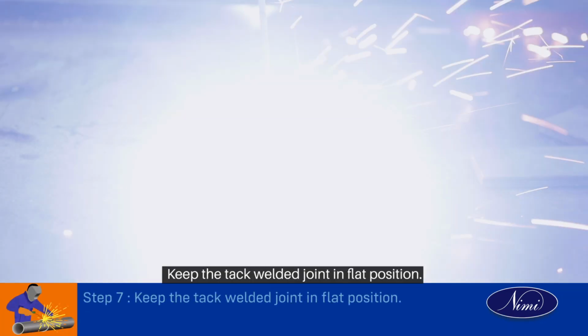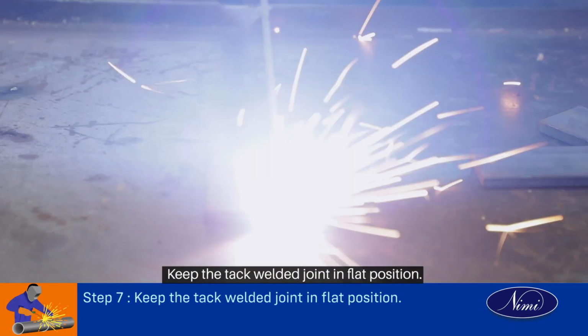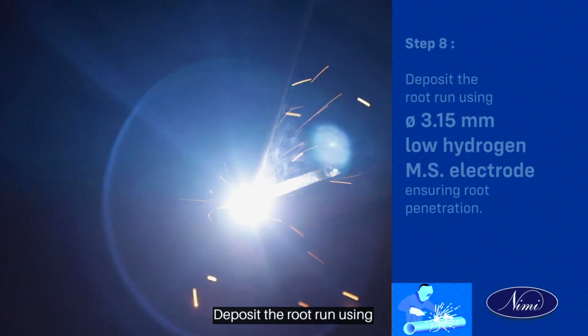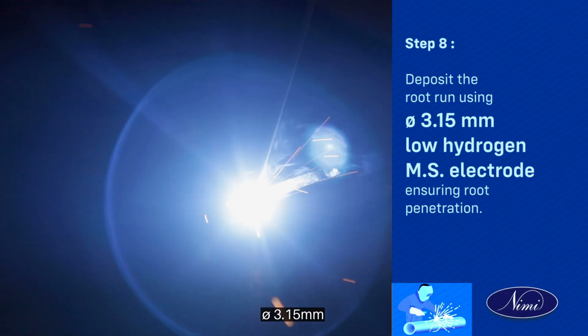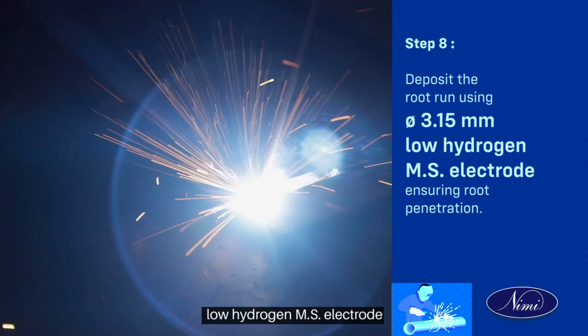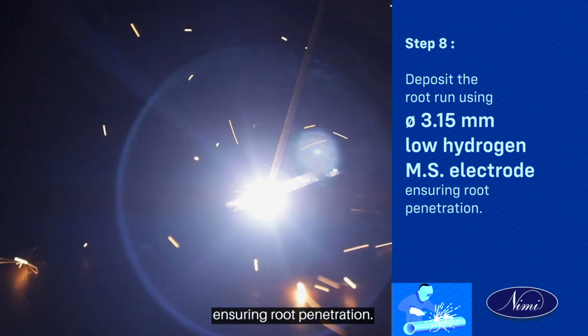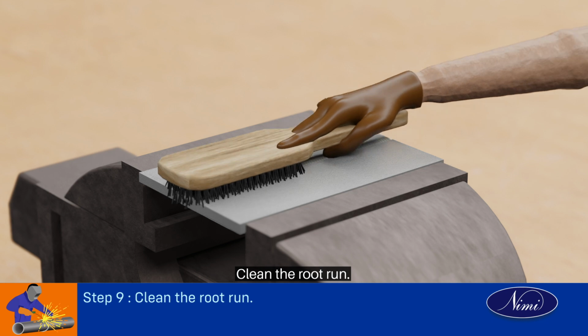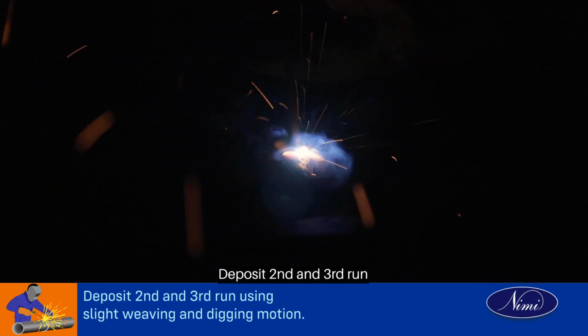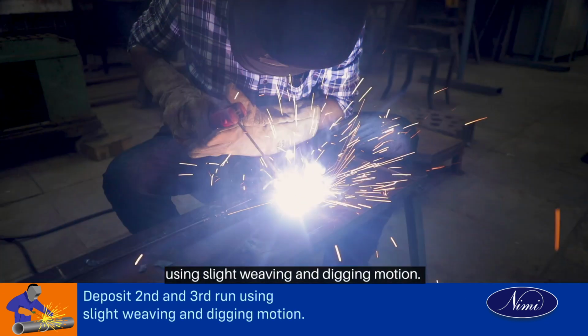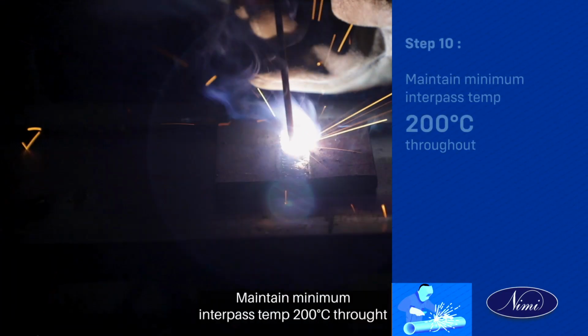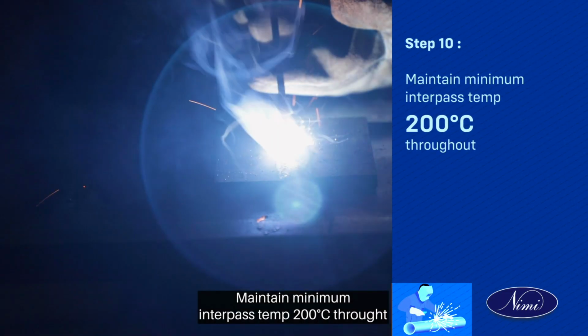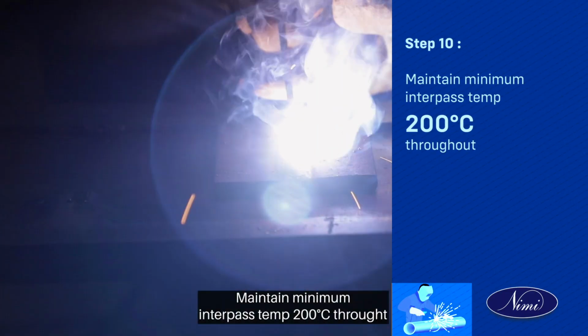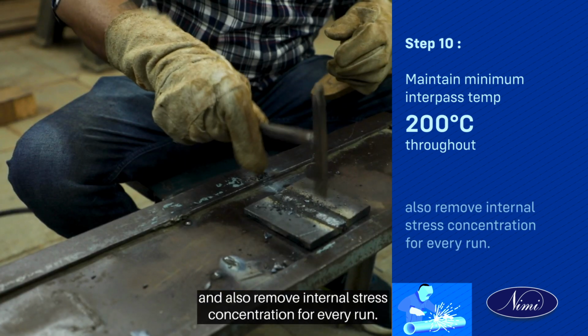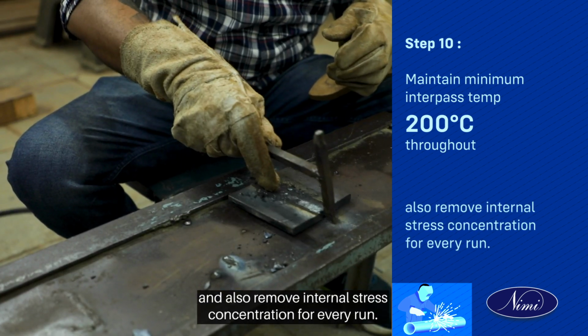Step 7. Keep the tack welded joint in flat position. Step 8. Deposit the root run using ø 3.15 mm low hydrogen MS electrode, ensuring root penetration. Step 9. Clean the root run. Deposit second and third run using slight weaving and digging motion. Step 10. Maintain minimum interpass temperature 200 degrees Celsius throughout and also remove internal stress concentration for every run.